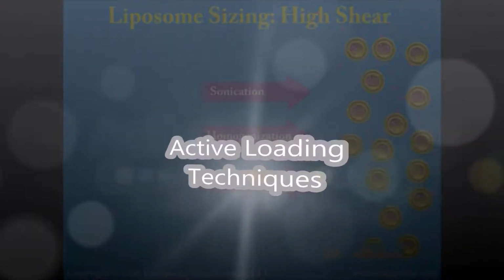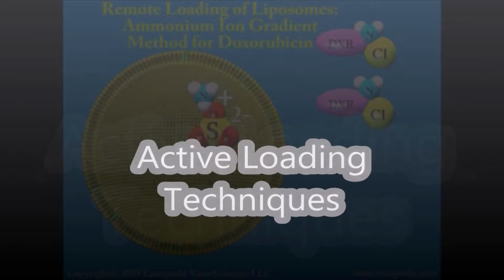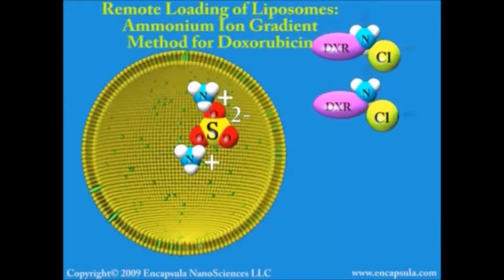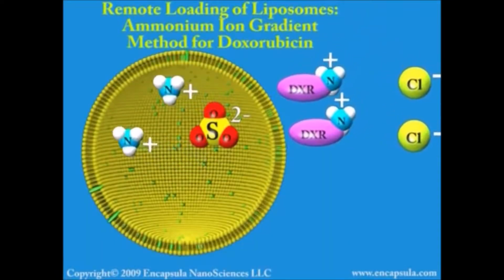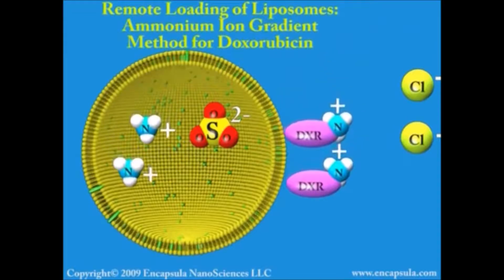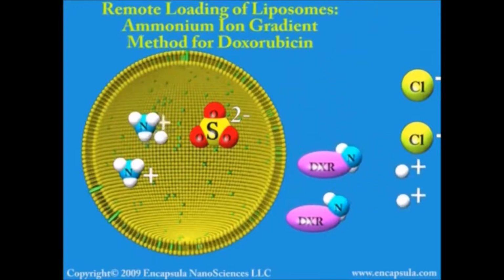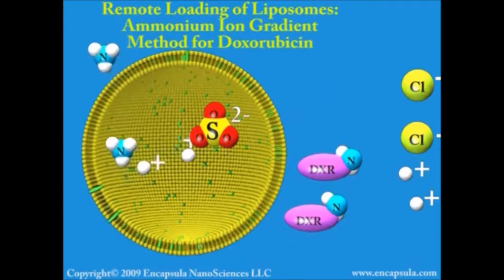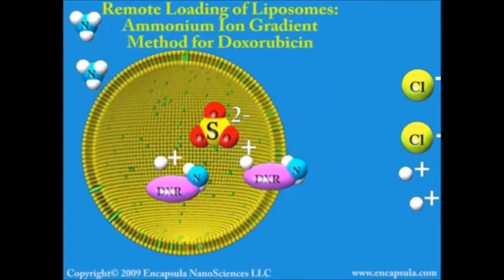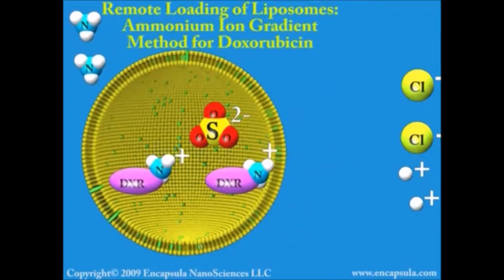Most water-soluble compounds must be present at the time the liposomes form to be encapsulated. Some ionizable compounds can cross the membrane in their neutral form and be converted to an insoluble salt form inside the liposome. This remote loading technique allows drugs to be loaded into liposomes after the liposomes are formed, but is not widely applicable.